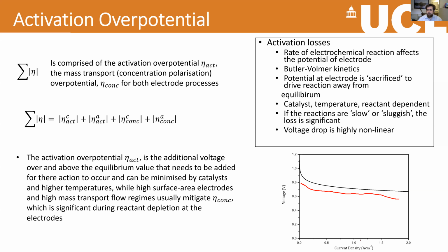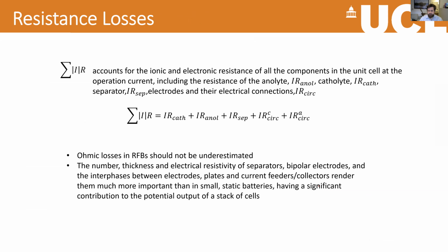Okay, so if we want to operate at useful current densities, i.e. have a useful amount of power coming out of the battery, then we have to sacrifice some of the cell voltage in order to do that. And by using things like catalysts or changing the temperature of the reactant, we can try and minimize these voltages. But if the reactions are very slow or sluggish, then we actually have quite a significant voltage loss in this case. So we want to try and minimize these activation losses or overpotentials.